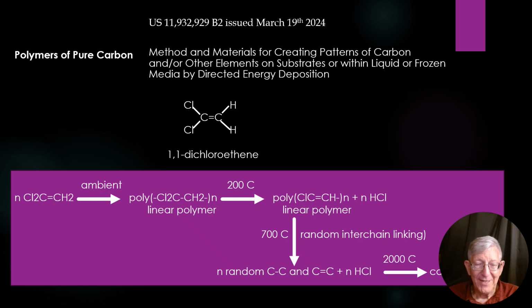It turns out that if you heat this stuff up to around 700 degrees, you do split out another mole of hydrochloric acid, but there are other reactions that are going on in there, and they're probably Diels-Alder 2+4 cycloaddition reactions, which gives you cross-linking, which you want, but it gives you random cross-linking that is not concerted with the appropriate loss of hydrochloric acid. And so you actually get a randomized cross-linking mess, which does conduct electricity, but it's certainly not carbon nanotubes or graphene. But we're not really expecting to have perfect material because we're just going to try to make some electrical components out of it.